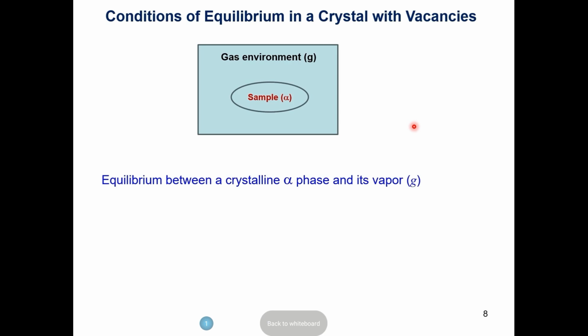That's thermodynamics. If you suddenly cool your sample, out of that equilibrium, it will violate that, meaning that you have created a state in terms of amount of point defects with a kind of metastable defect state. Meaning that if you heat treat the sample now, the amount of vacancies you create will change, and eventually you will go to this equilibrium number of vacancies. And we're showing that when it gets to that equilibrium level, the chemical potential, which is an important property of the solid, the chemical potential of those vacancies will stay constant. Okay, so that's the exercise that we do first.